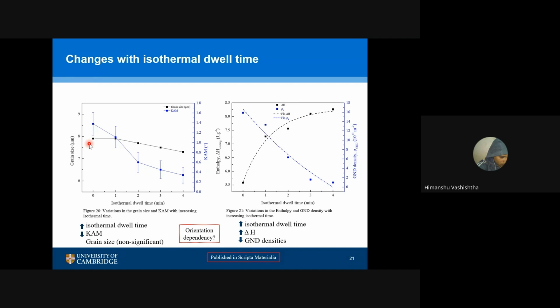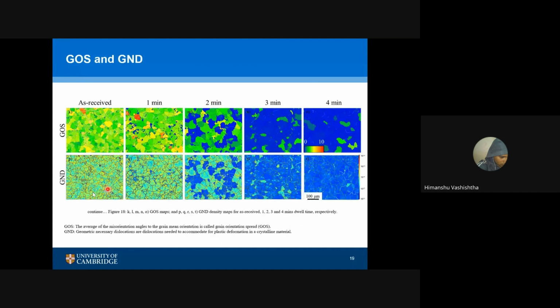That's well within the error range. However, the kernel average misorientation, or the dislocations, are really coming down. We plotted a graph between the enthalpy change and the GND density. Enthalpy change means area under the curve, and this black line is increasing, meaning the enthalpy of transformation is increasing. Now we have to supply more energy to transform our material. However, the GND density is coming down, as you remember from the EBSD data.